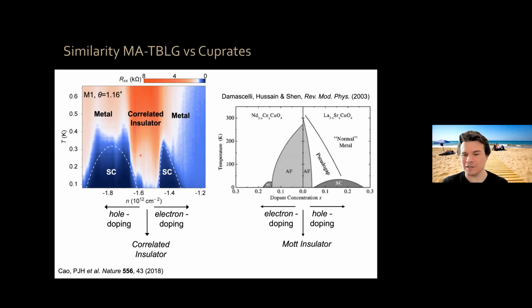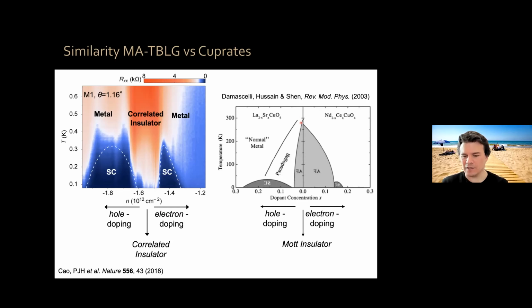Now, when my students showed me this for the first time, I was immediately fascinated because of the hundreds of times that I've seen phase diagrams such as this. This is the phase diagram for high temperature cuprate superconductors. Let me flip this axis so that they correspond to electron hole doping similar to us. In high temperature cuprate superconductors, 0 doping means 1 electron per unit cell, and you have a Mott insulator, a correlated insulator. If you add holes, you have a big superconducting dome. If you add electrons, you have a smaller superconducting dome. In magic angle graphene, this correlated insulating state corresponds to 2 holes per moiré unit cell. If you add extra holes, you have a superconducting dome. If you add extra electrons, you have another superconducting dome.